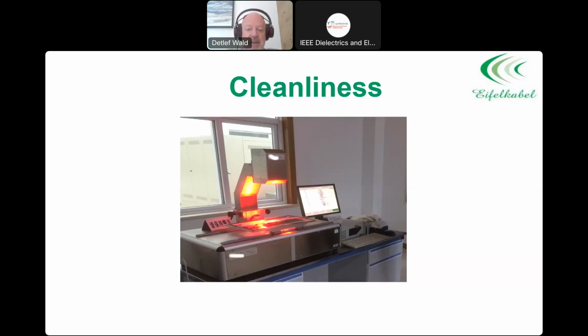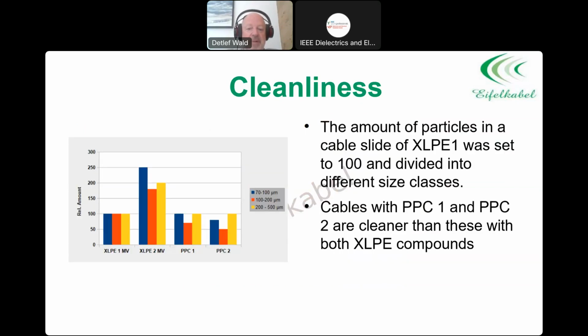Here's a test that we have done. We looked at what contamination is in the cable, and we compared polypropylene compounds with XLPE compounds. On the left-hand side you see two commercial XLPE compounds that are in the market, and XLPE 1 is just standardized to 100 in each contamination class, and the other ones are put in relation. So at least in that test, I can clearly say that polypropylene is in the same contamination range as a medium voltage XLPE compound.